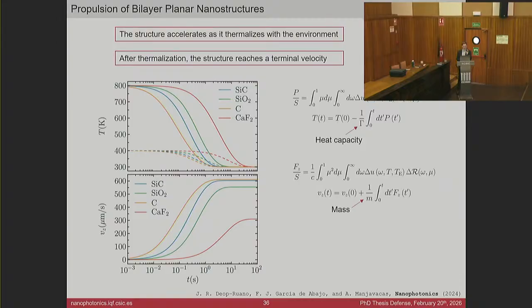So if we go to a lower initial temperature of 400 Kelvin, we can see that we obtain a smaller terminal velocity. And actually, by using our ideal system, we can explore this dependence of the terminal velocity on the initial conditions, and see that it is linear in the difference between the initial temperature of the nanostructure and that of the environment.